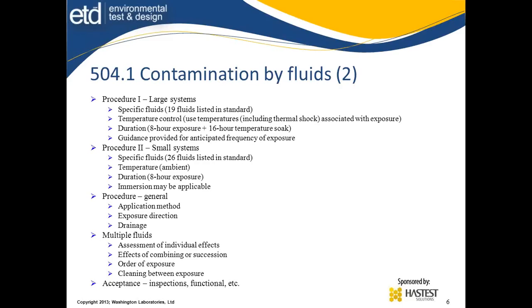The duration normally calls for an 8-hour exposure to the fluid and 16-hour temperature soak. So we're soaking at some temperature associated with the device. It's either hot, cold, or whatever is appropriate. And it could be multiples. The guidance is provided for anticipated frequency of exposure. There's some additional information in the standard. But really we need to come back to the life cycle control plan. What is this thing going to see in its lifetime?